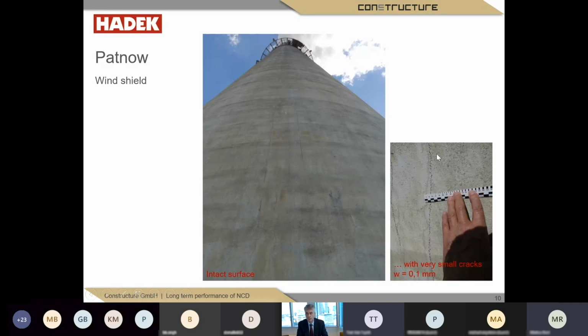On the chimney, we found only very small crack widths of about 0.1 millimeter and a uniform distribution of these cracks on the circumference. So the reinforcement corresponds with constraints caused by the temperature difference from the inside to the outside, reduced by the thermal insulation of the Pennguard block lining system. So we detected no deficiencies on the windshield caused by cracking.